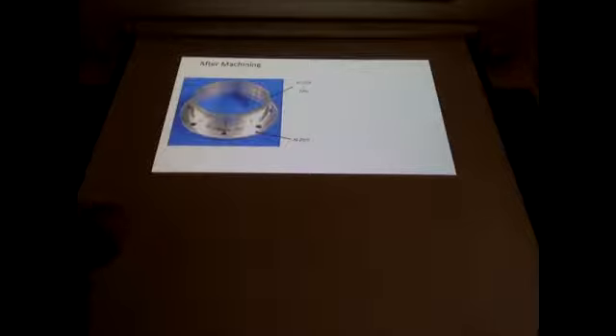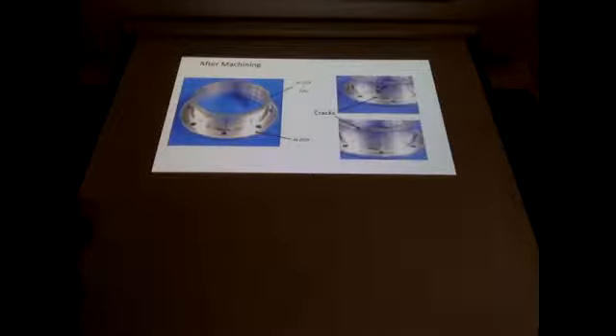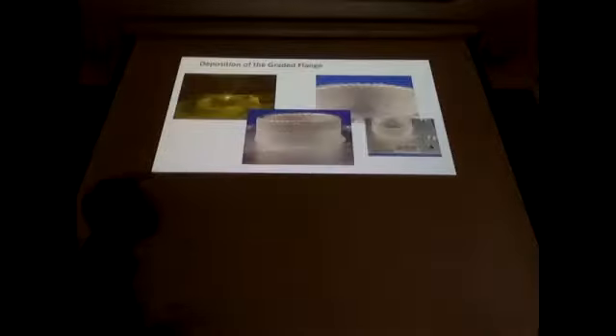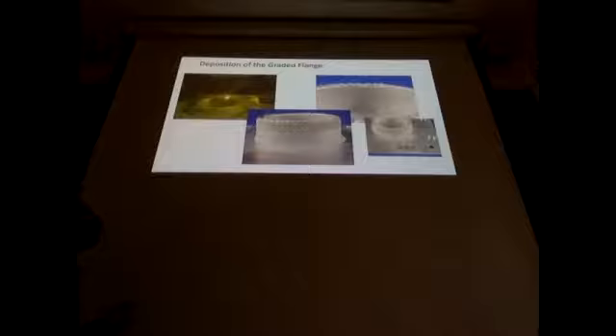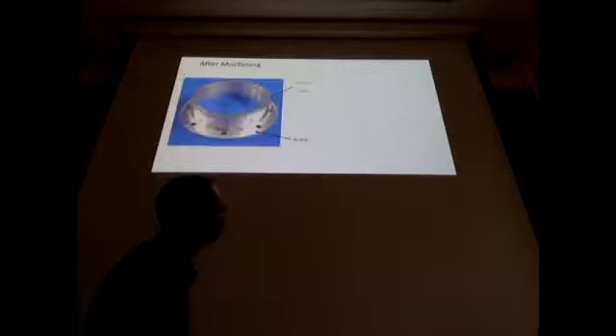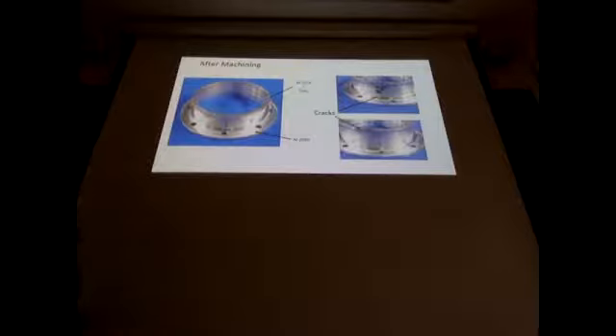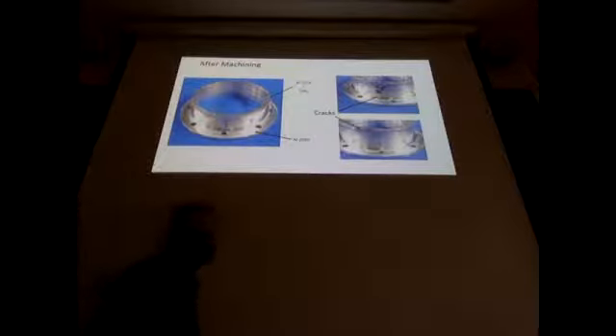We did have a few defects because we didn't have too much funding to try this out. But these defects weren't really related to the problem with the composition. It was a problem with our processing side. We had a stall in our Optomec system where the powder clogged the nozzle. We had to stop and restart, and it left a mark here on that area. The other issue is when we made the top, it wasn't exactly very smooth. I can go back here, and that little area caused a bit of an issue and ended up showing some cracks here that we just couldn't machine out.